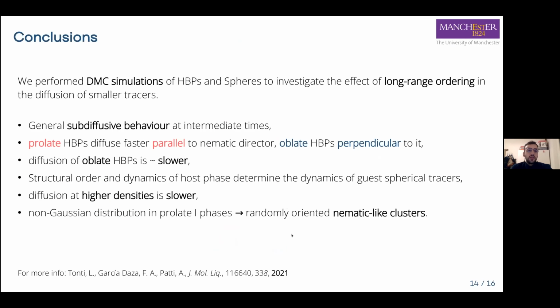So in conclusion, in this work, we performed DMC simulations of hard board-like particles and hard spherical tracers to investigate the effect of long-range ordering on the diffusion of smaller tracers. We observed the general subdiffusive behavior and the formation of temporary caging effect at intermediate timescales. We observed anisotropic diffusion due to the long-range ordering of the phase.